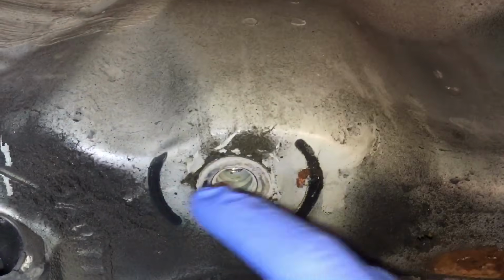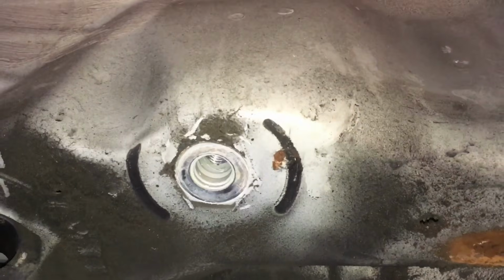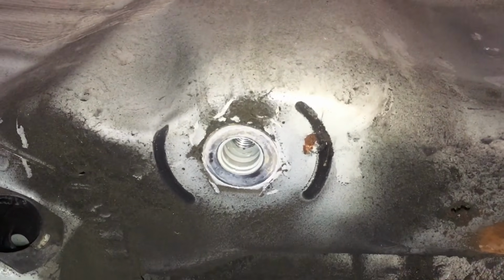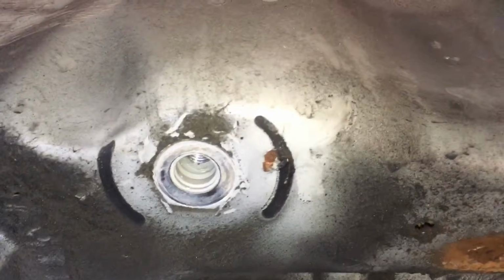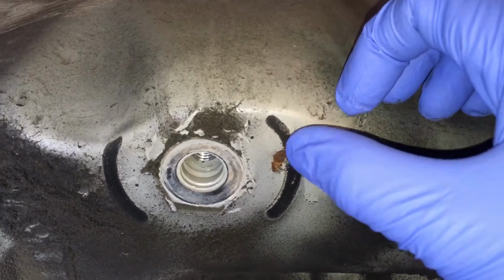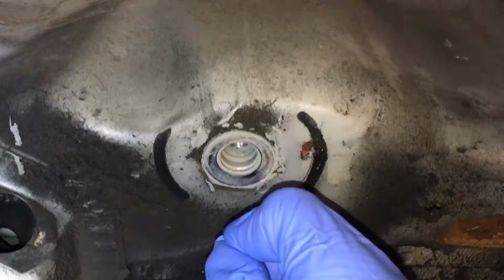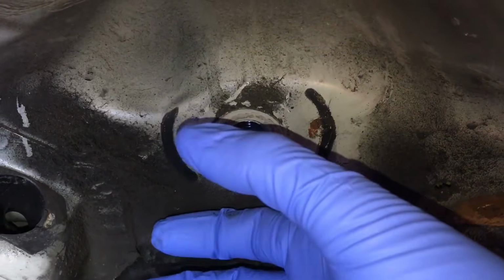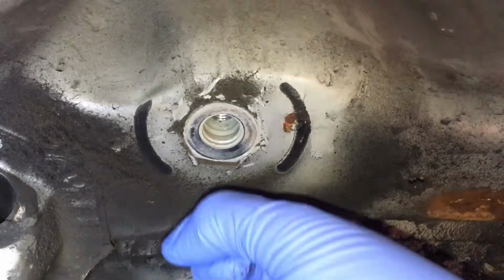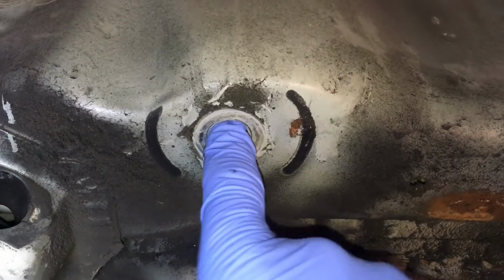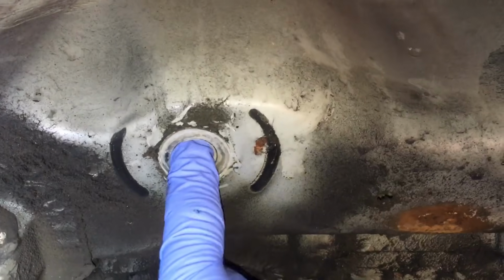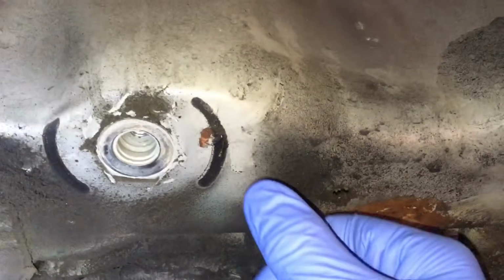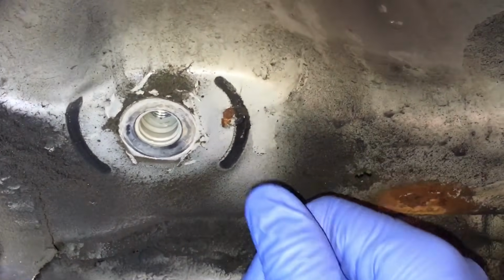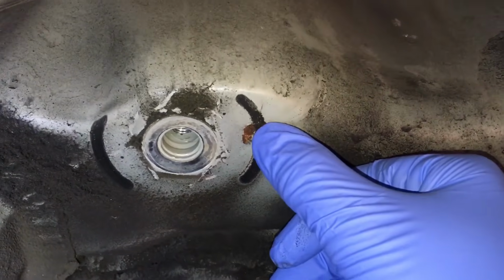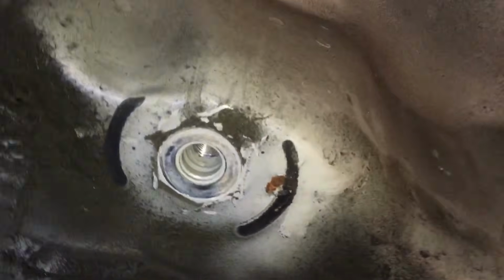Now this is also interesting as well. The bush imprint is very strong. You don't normally see so much of a bush imprint on that, so that's possibly why that spot weld is cracked a little bit prematurely, being it's only 59,000 miles, because we know, everybody knows that the torsional load and the movement of the subframe and how the energy enters the chassis is pivoting and tipping the studs that are in here, which is what helped break the spot welds by flexing the two panels apart. But also the bush impact into it has a very slight bearing on it as well, which may be why we've got crack coming out of there already at a low mileage late vehicle.